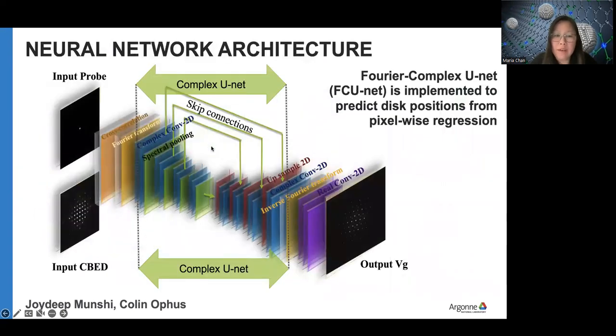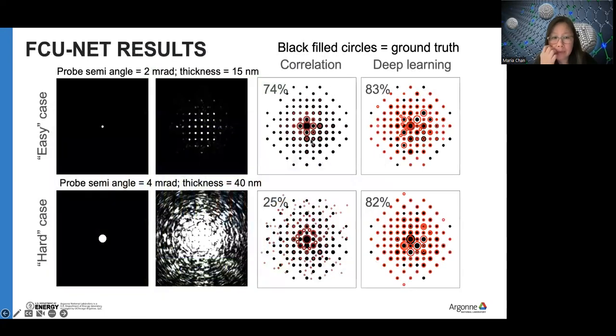So with those training data, we then started to train different networks to see if the results are good. We started with the more obvious choice of a UNet, and then got reasonable results. But then we realized that we were working on this problem where we were looking at a reciprocal space image, but the symmetry is contained or is there in the real space image. And we tried to see if we can incorporate some of that in. So we actually use a Fourier transform within the neural network and carry out complex convolutions. So there are real and imaginary parts in this. Because it's a Fourier complex UNet, we call it FC-UNet, that actually gave much more accurate results than the simple UNet. I'll give you some examples here.